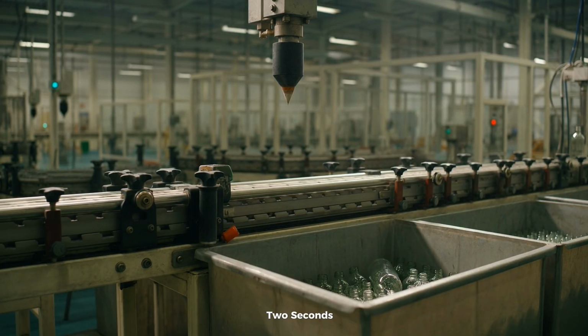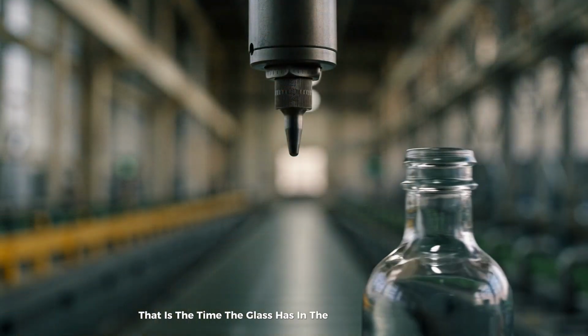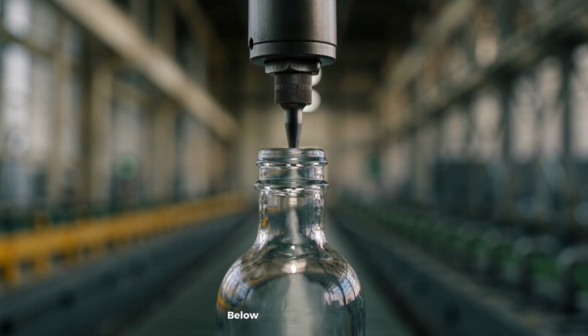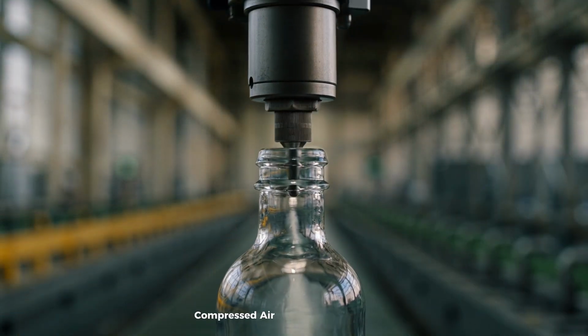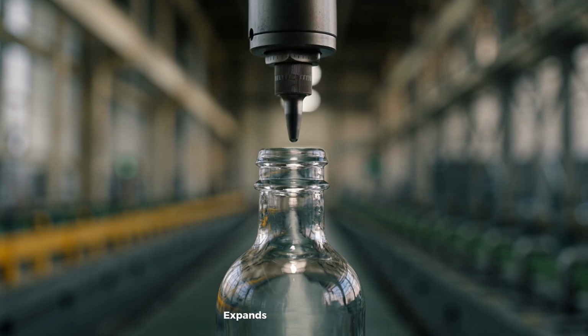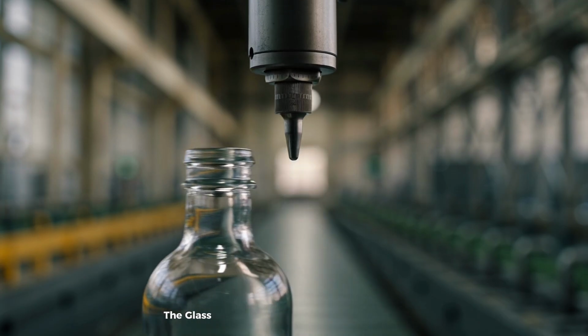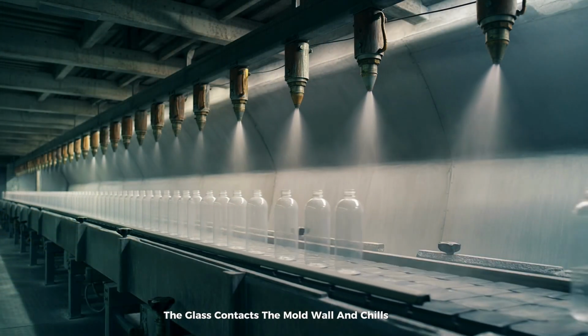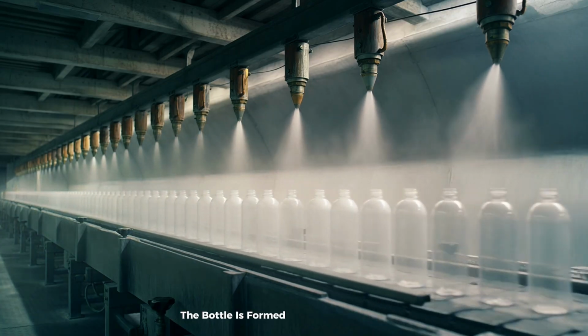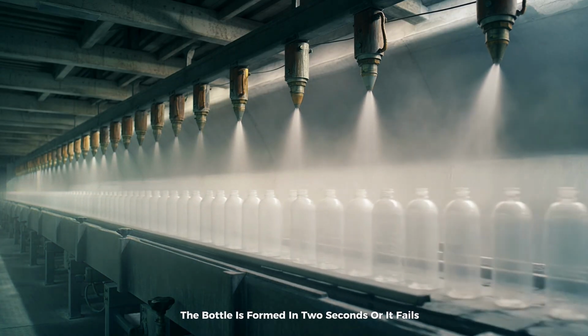2 seconds. That is the time the glass has in the blow mold before it cools below forming temperature. Compressed air enters through the neck, expands the parison outward. The glass contacts the mold wall and chills instantly. The bottle is formed in 2 seconds or it fails.